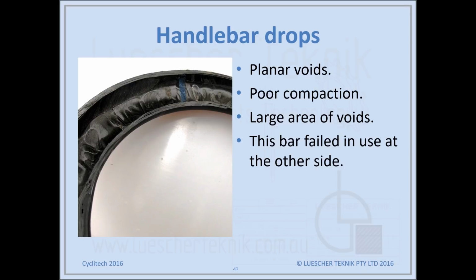Now, handlebar drop. This handlebar was sent in because the other side actually failed during use while the person was riding along, and so it was sent to us to assess why it failed. But then when we scanned other areas of the bar, the drop on the other side that didn't fail, we found, you can see all through this bend here, there's planar voids. Also through this end, you can see large planar voids. Porosity through here. You've got resin pooling. So there's a whole bunch going on. Poor compaction, large voids. So it's not surprising that the handlebar failed with those flaws.